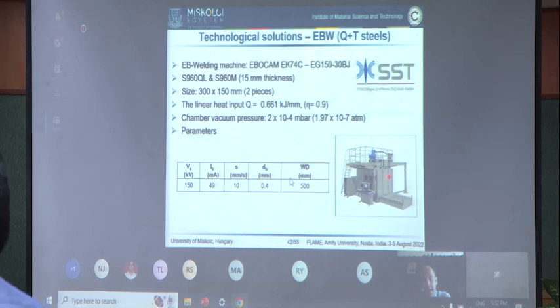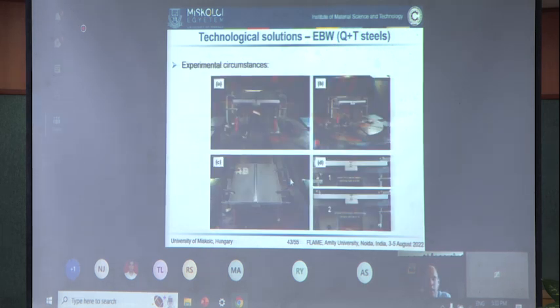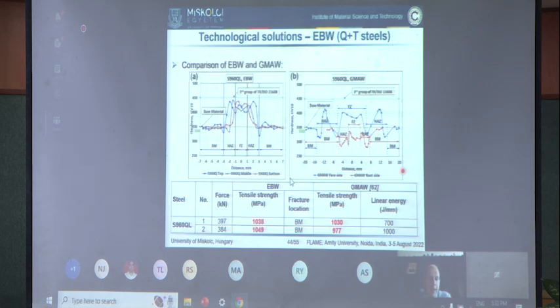Our last example will be a solution for electron beam welding of thicker high-strength steels, so for quenched and tempered and TMCP high-strength steels. With electron beam welding, we can use a one-pass square groove welded joint, even at a thickness of 15 millimeters. Here you can see the experimental circumstances in the vacuum chamber of the equipment, and here you can see a result.